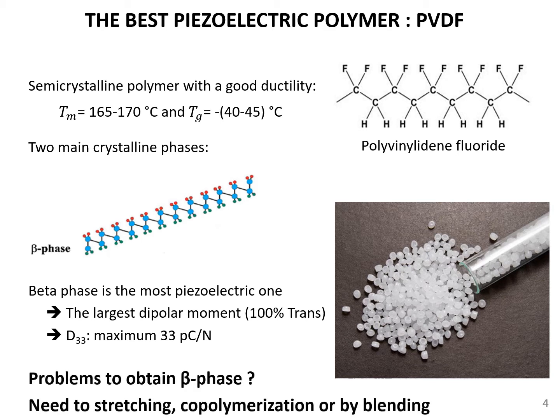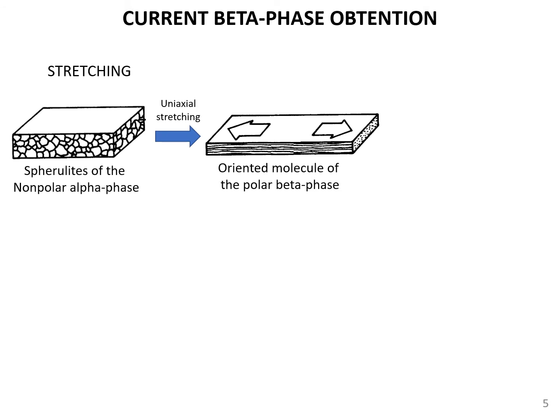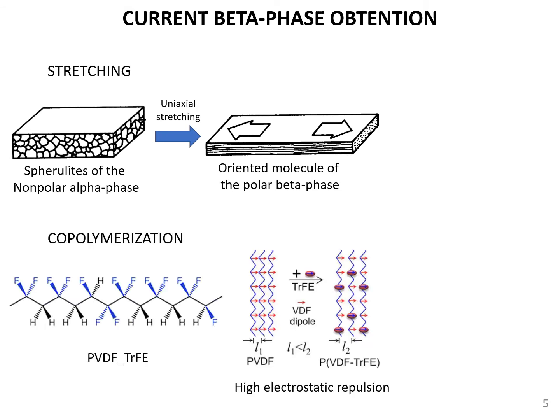However, to obtain the beta phase, you need to apply an indirect approach like stretching, copolymerization, or blending. The current way to obtain the beta phase can be based on the stretching approach or by copolymerization. In the case of stretching, you need to apply orientation to any PVDF films in order to crystallize the PVDF as a polar phase.